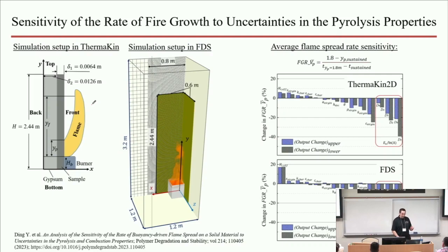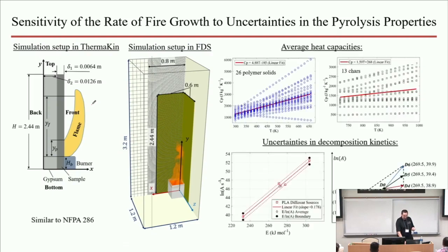And the answer to that is that in this particular model, we in fact take into account the dependence of heat capacity on temperature. You see the red line here? It is actually what we feed into the model. This data is the heat capacity dependence on temperature for a variety of materials. They were all taken as temperature dependent, and our model takes that into account. So there is no limitation in this model that the heat capacity doesn't depend on temperature. We assume within the model that it's linearly dependent on temperature.